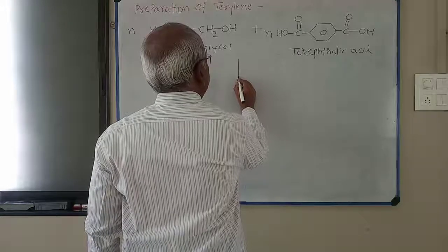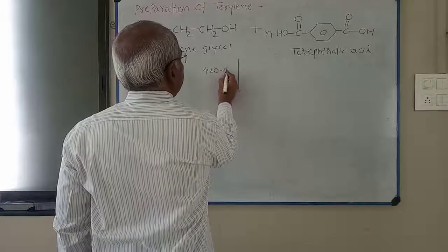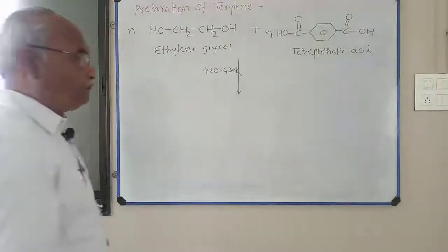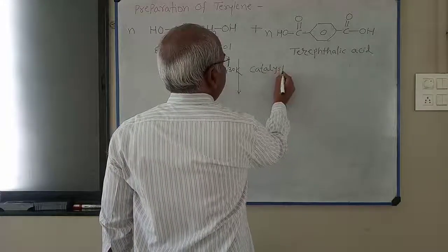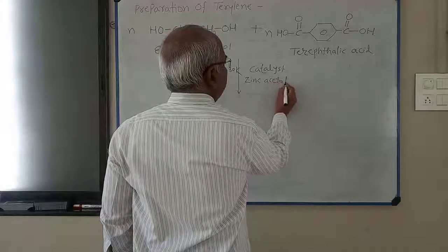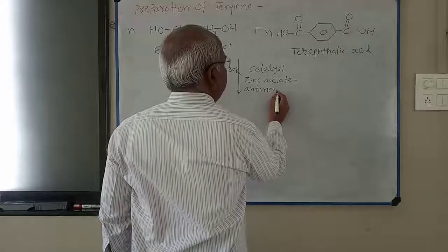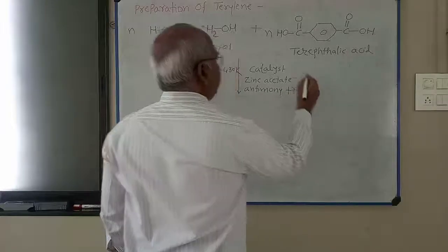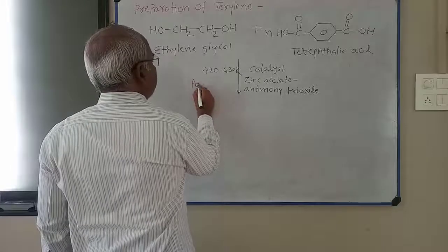Both these raw materials are heated at about 420 to 430 Kelvin in presence of catalyst, zinc acetate and antimony trioxide. Polymerization reaction takes place.